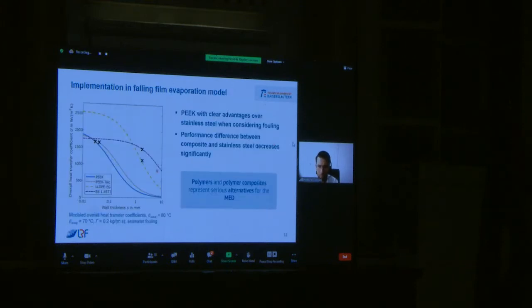For better comparability of all materials, I've added the asymptotic fouling data of the experiments to the falling film evaporation model, which I presented earlier. And it can be seen that stainless steel in particular is very strongly influenced by the fouling resistance. As a result, the performance difference between the composites and the stainless steel dropped sharply, which was already evident in the experimental data. However, since deposits also form on the investigated polymers, the feasibility of cleaning in place is of great interest, because a simple cleaning in place, for example, can reduce downtimes and hence reduce costs.